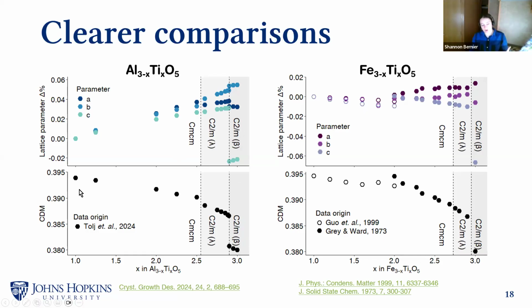And what really is interesting here is when you compare to a similar material that has the same space groups, but it has a different atom here, iron titanium oxide. And you can see when they're plotted on the same set of axes, as opposed to when the lattice parameter deviations are plotted separately, they actually follow very similar behavior on their way to this final C2/m beta phase.